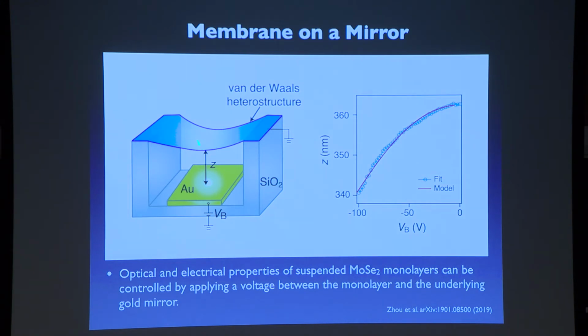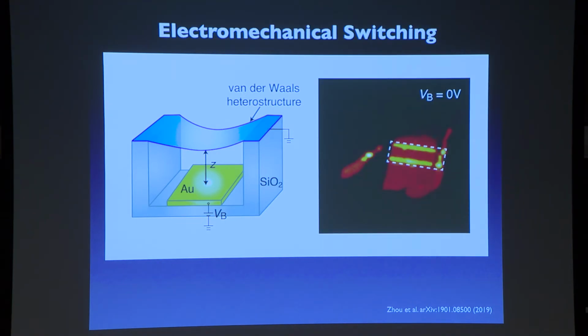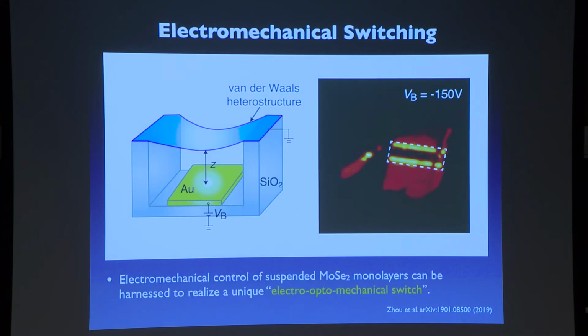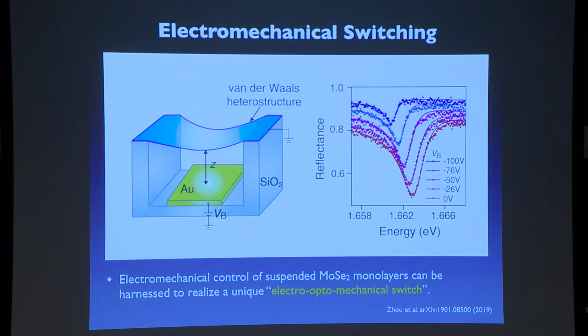Then, by applying a voltage between the two, you can control the distance between them, because you can essentially make a capacitor, make it go thinner, smaller and larger. You can control the distance between them. What happens if you change the distance between them when you shine light that is resonant with the excitonic transitions in this particular sheet? Well, it turns out that you can change the brightness of the reflection at will by the voltage that is applied, which changes the distance between the two. And more importantly, you can change the line width quite a bit, by a factor of 3 or 4. By now, we can change it by a factor of 4 or something like that.